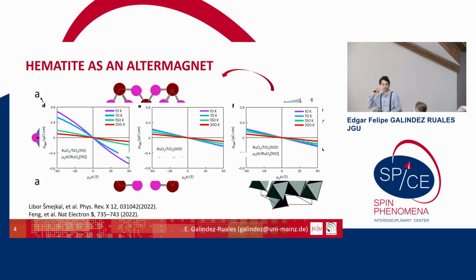This starts at the spin reorientation transition, and we know that we can also have a spin reorientation transition in hematite. Someone in 2017, if I'm not wrong, reported an anomalous Hall effect in hematite, but it was one report of some anomalous effect, and a lot of people were saying no, there is no anomalous effect in hematite. So we looked a little bit more inside, and we asked what is happening, what is the trick, and the percentage of doping is quite tricky.